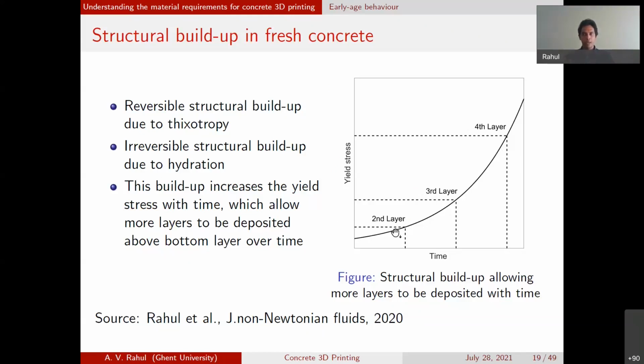For example, if you have a mixture that has a very rapid evolution of these material parameters, then you can print quite fast, because you are increasing the load on the bottom layer, but at the same time the bottom layer's material parameters are also increasing at a quite rapid rate. On the other hand, if you're printing with a material that doesn't evolve fast enough, then you may need to slow down your rate of printing. So we need to characterize these material parameters, which is the strength the material can have, as well as the modulus values. And then we also need to know the rate of evolution of these material parameters. How do these material parameters change with respect to time? Both these data are required for us to design the print process.